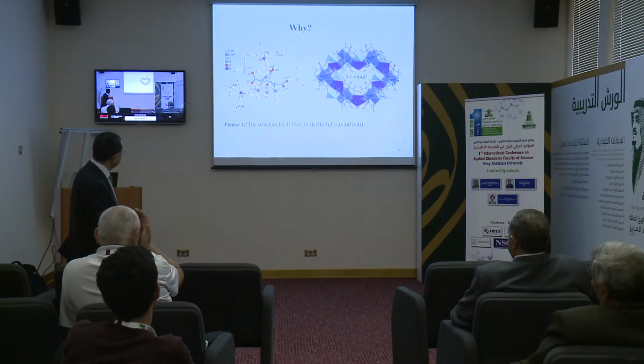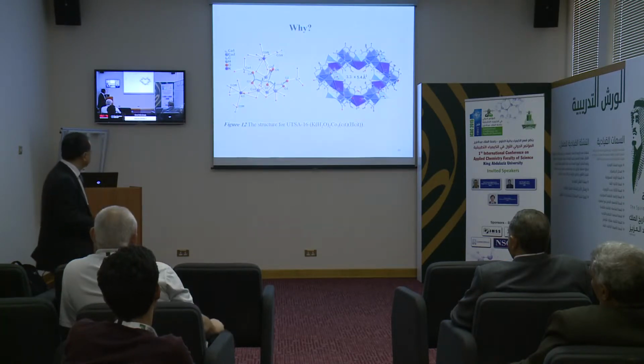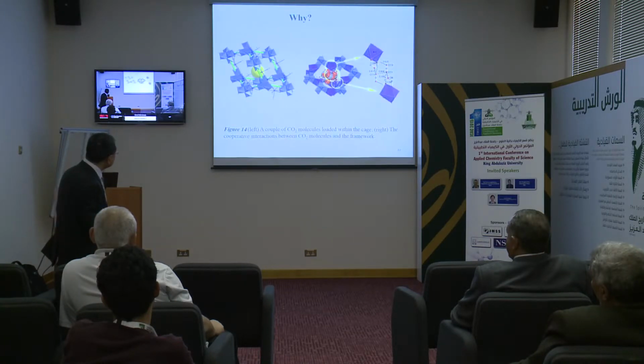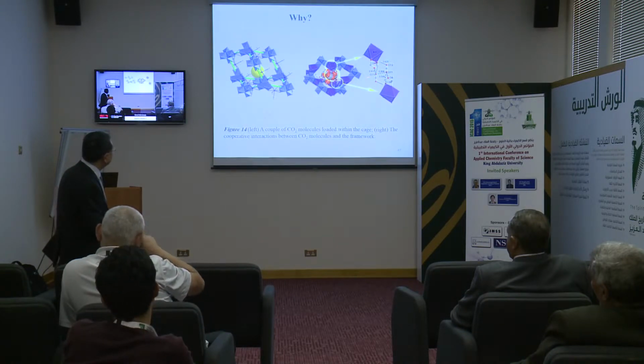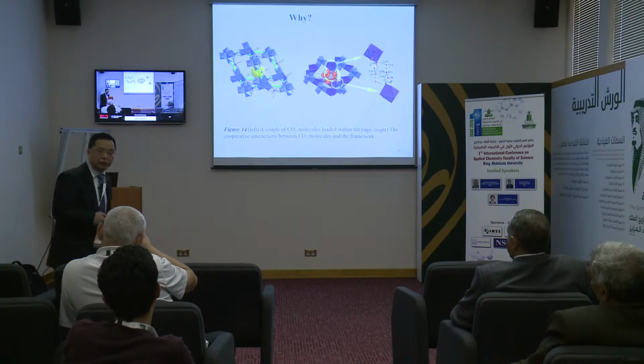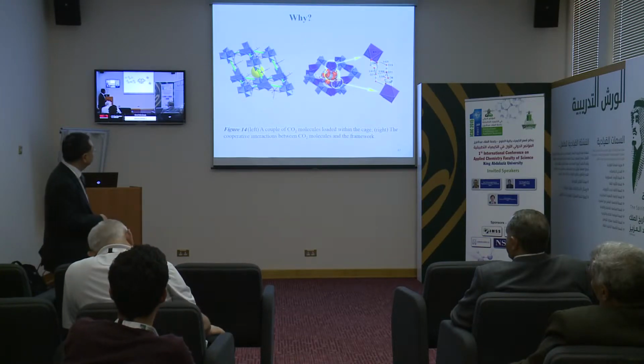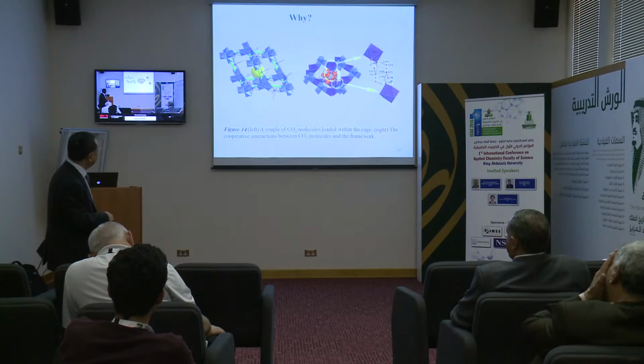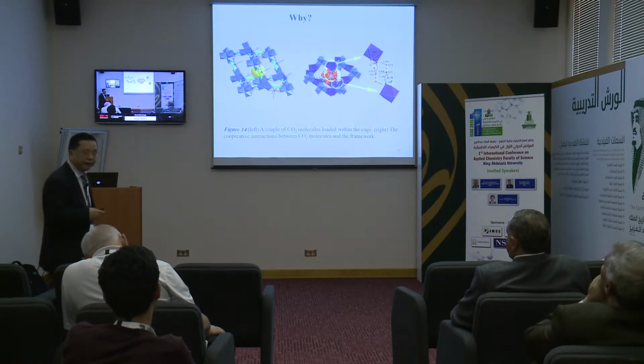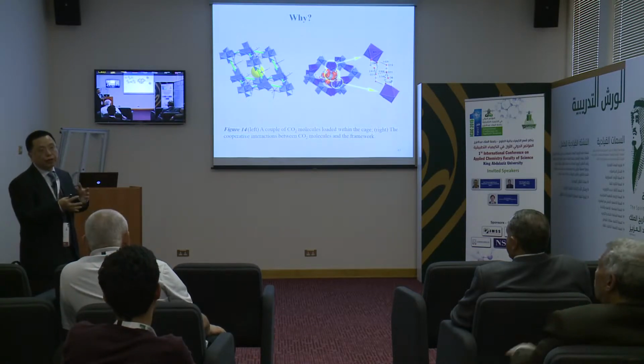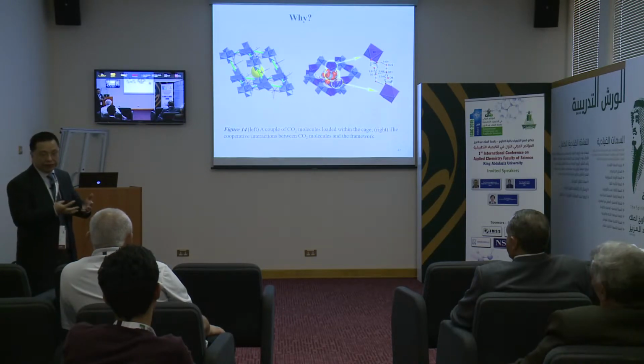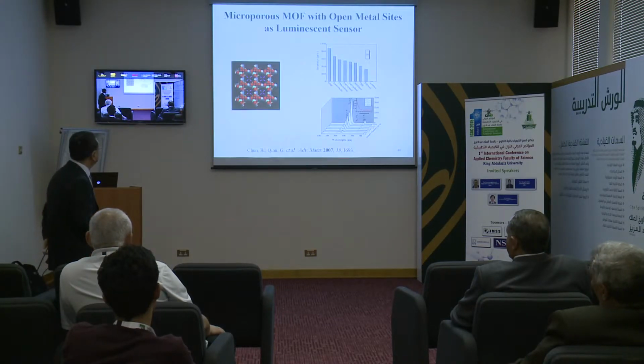So for scientists, we need to know the mechanism. One more thing I want to mention: this is a very simple citrate, a very cheap organic linker. The uniqueness here is that the pore is quite unique. And a neutron diffraction study indicates that the terminal water molecule also plays quite an important role in the specific recognition of carbon dioxide. This cage is quite suitable, only about 4.5 angstrom, but it can capture 4 molecules of carbon dioxide. So overall, high density of carbon dioxide. That is a feature.